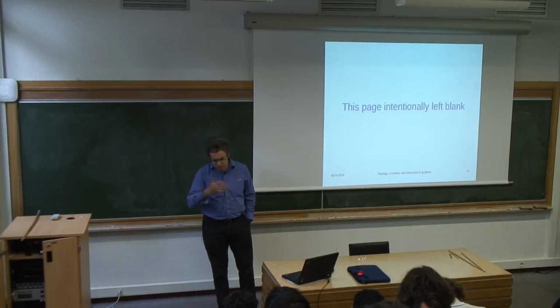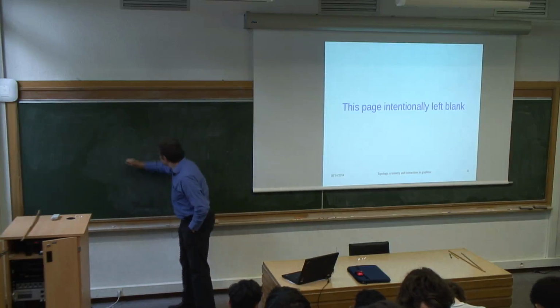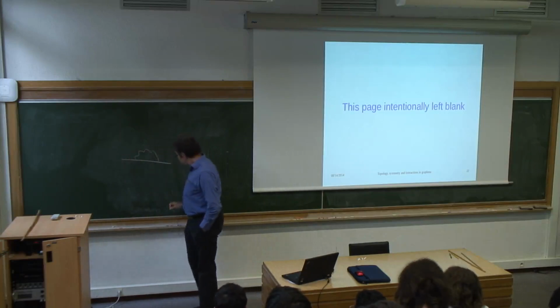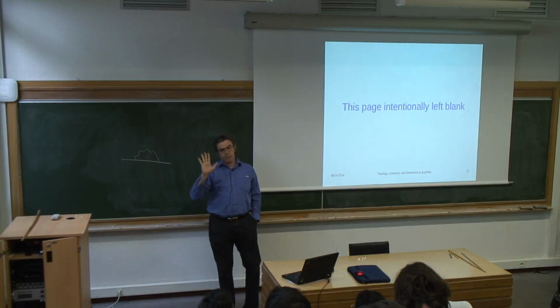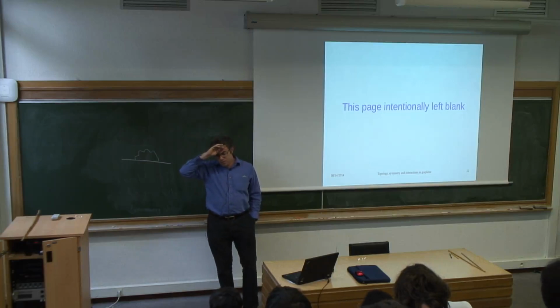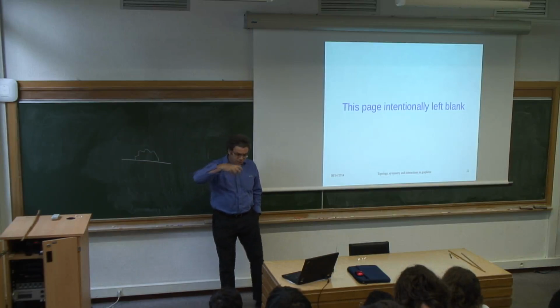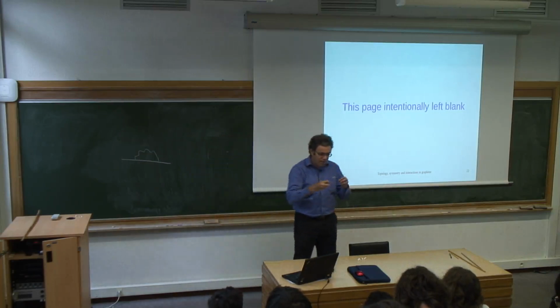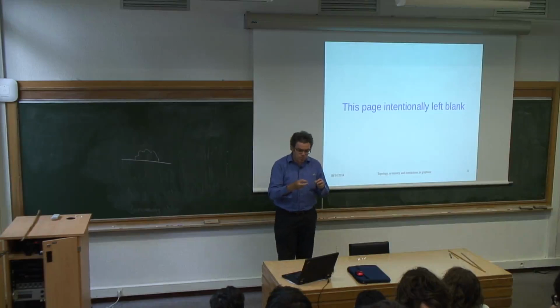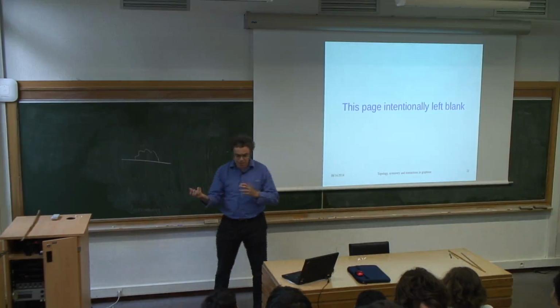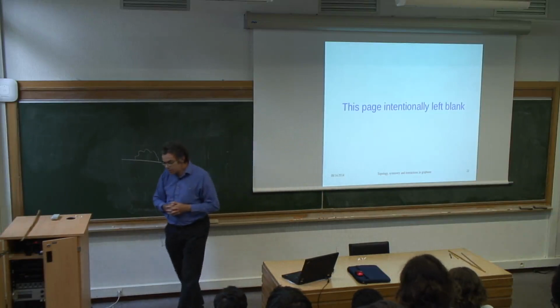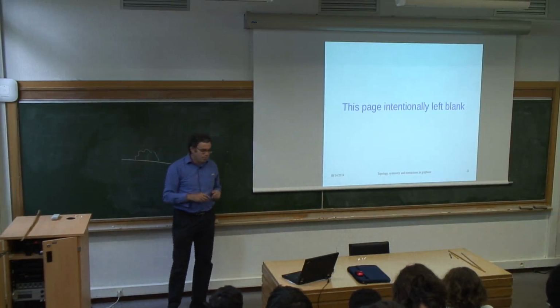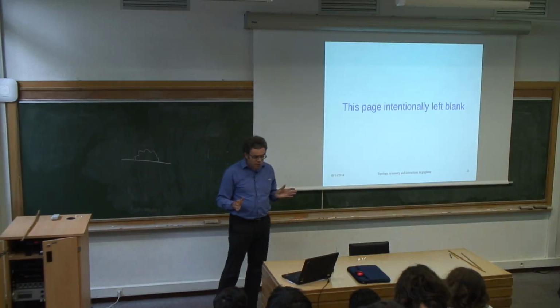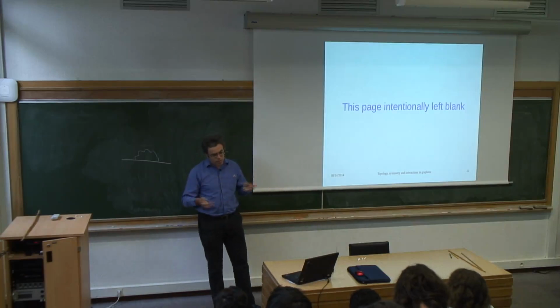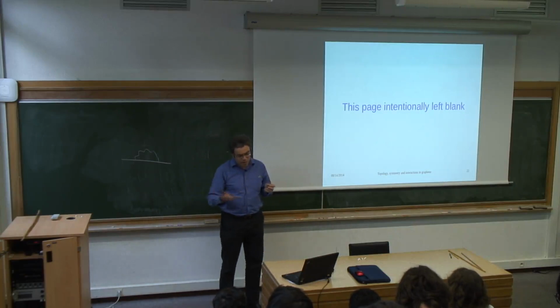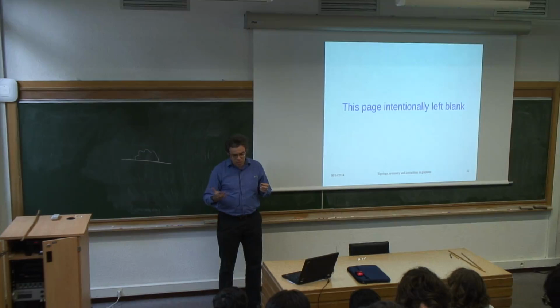At least on perturbation level, this is very clear if you think about this diagram. And then there are more complicated cases about what happens in a strongly correlated system, like if you take helium-3, then helium-3 interactions with helium-3 are dominated by contact short-range interactions, so it should be non-retarded and would produce, according to what I said, velocity enhancement. However, people believe that helium-3 is so strongly interacting a system that it's actually on the verge of some Stoner type instability, and so there are many low energy excitations, spin fluctuations, which are